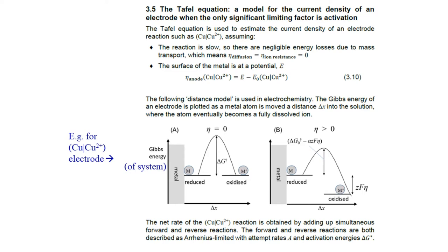Some assumptions we are going to make in this model are, first, the reaction is slow, so there are negligible energy losses because of mass transport. So that means that the overpotential eta, the polarization loss, eta due to diffusion and due to ion resistance, are both zero. We, in fact, don't even need to realize those losses might be called polarizations. Second assumption, we are going to assume the surface of the metal is at some potential E. So the surface has reached a single uniform surface potential of E, as given in equation 3.10.